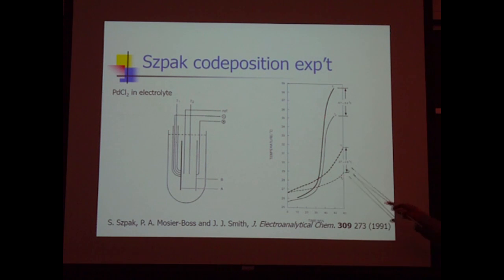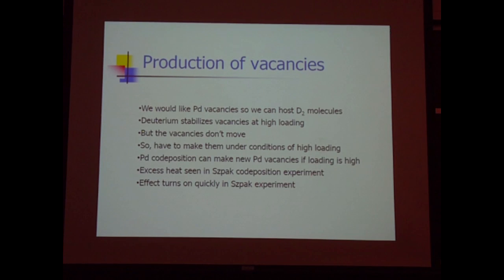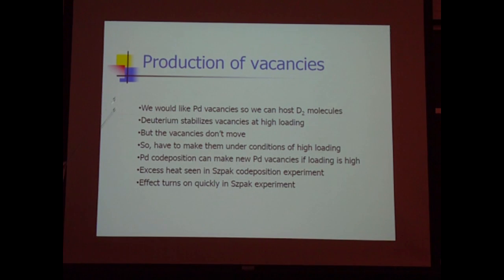I'm looking at this and thinking, well, co-deposition of palladium at high loading, if the thermodynamic arguments are right, then the co-deposition should be forming high vacancy Fukai phase palladium. So the co-deposition at high loading should be making the environment that we need to see molecular deuterium. So we like palladium vacancies so it can host the molecules. Deuterium and hydrogen stabilizes the vacancies at high loading, but the vacancies don't move. So if you like, we can make them anew if we achieve high loading and make new palladium. If we co-deposit palladium onto the surface, then by the thermodynamics of vacancy stabilization, we'll be making a high vacancy concentration in the co-deposit regime.